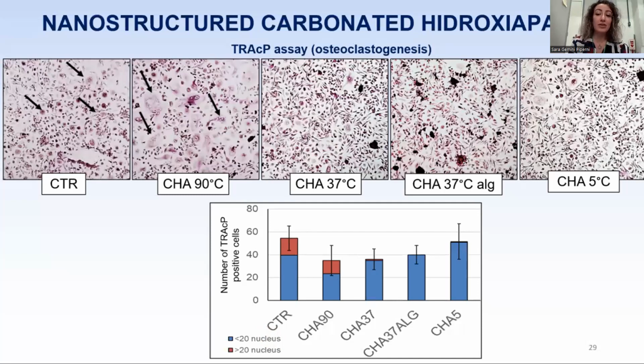However, the same hydroxyapatites have different effects on osteoclastogenesis. Acid phosphatase is a marker of mature osteoclasts that is used to verify changes in osteoclastogenesis, osteoclast formation from monocytes. So these assays show monocytes exposed to different hydroxyapatites in osteoclastogenic medium, that is a medium supplemented with osteoclastogenic cytokines to induce osteoclastogenesis. And we show a larger osteoclast size on exposure to the 90 degrees material. So it is a bigger osteoclast formation with more crystalline materials, but a higher osteoclast number when monocytes were exposed to the amorphous materials.